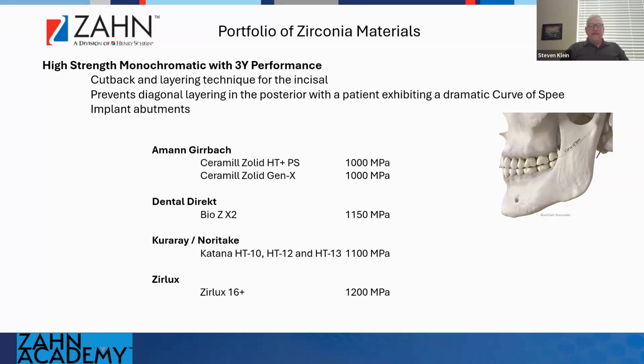In this lineup, again, Amann Girrbach has the solid HT plus PS, meaning pre-shaded, 1,000 megapascals. They have the solid Gen X, also 1,000, and it's just a next generation reiteration within that company's lineup. Dental Direct has BioZ X2, a little higher megapascal at 1150. Kuraray Noritake has, again, the HT10, which is white, HT12 and HT13. These are at 1100 megapascal. And the HT12 basically means A2, A3, and A1.5 to A2, I would say, is even more accurate. And then the HT13 is really A3 to A3.5. So you select based on those shades that you need.